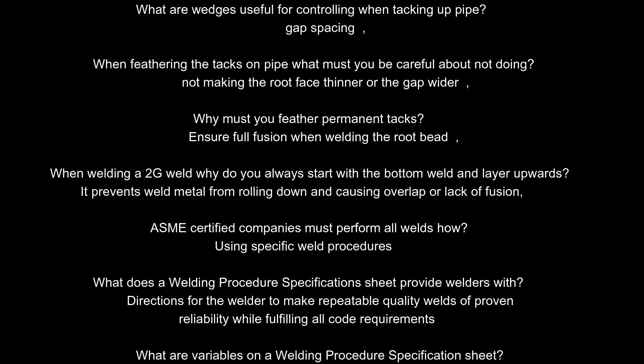What are wedges useful for controlling when tacking up pipe? Gap spacing. When feathering the tacks on pipe, what must you be careful not to do? Not make the root face thinner or the gap wider. Why must you feather permanent tacks? To ensure full fusion when welding the root bead.